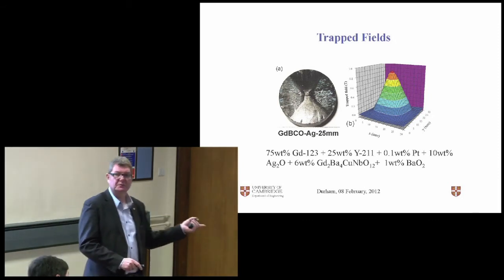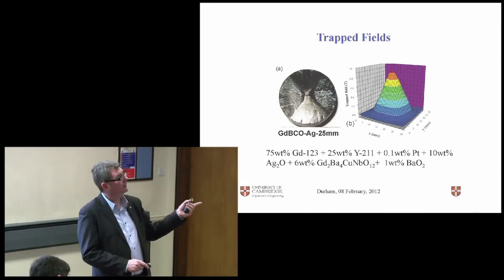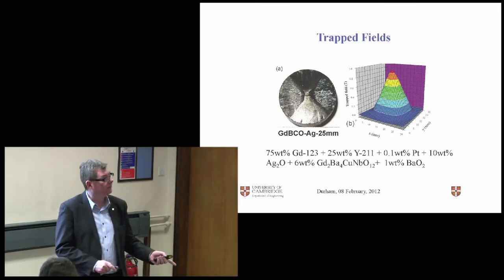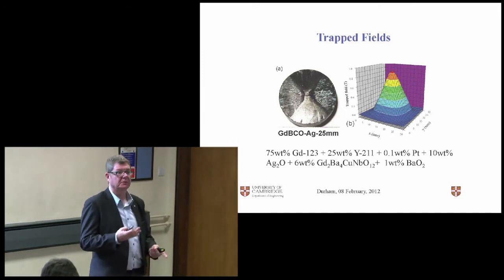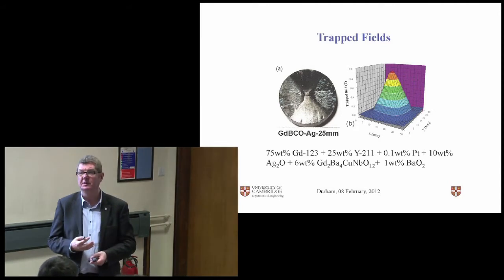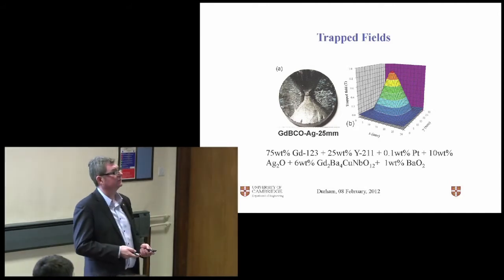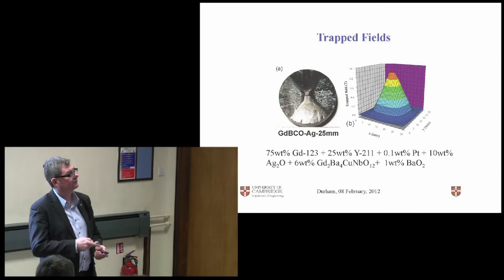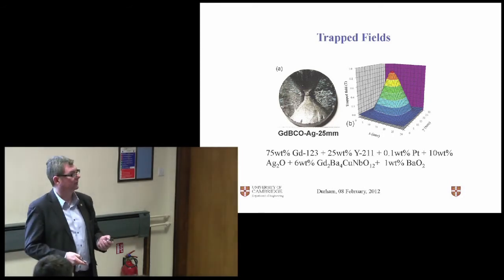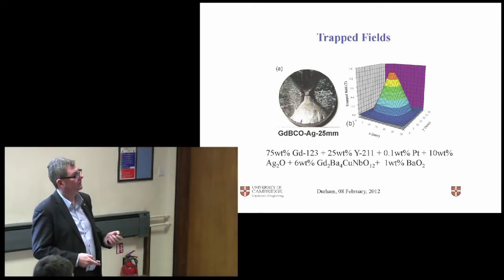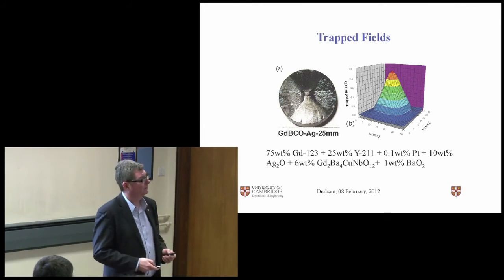And the whole point about bulk samples is that if you then levitate a permanent magnet using a bulk sample, that levitation is stable. So the pinning centers will resist motion. So rather than the unstable levitation you get with a bulk permanent magnet, with a superconductor, it's stable. And that's one advantage that superconductors have over conventional materials.